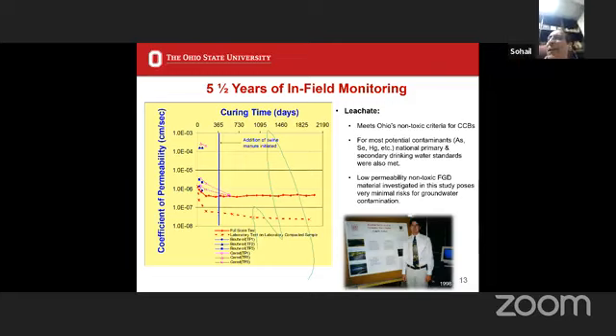I'm here and I would like to thank Dr. Butalia for the very explicit explanation. I would also like Dr. Butalia to comment further, that field permeability values are dependent on the method of permeability determination. If casing is used, and a soil column is introduced by drawing the casing up, then there is a kind of smearing effect also, and sometimes it is understood that the field values may tend to be lower than the representative values in reality because of the smearing effect on the inner surface of the borehole.